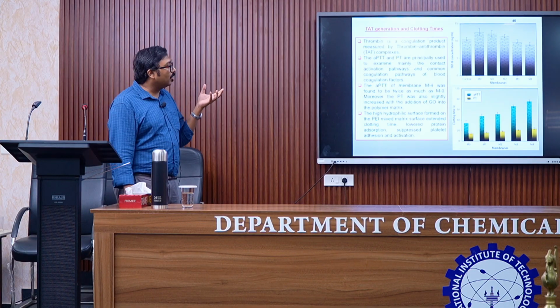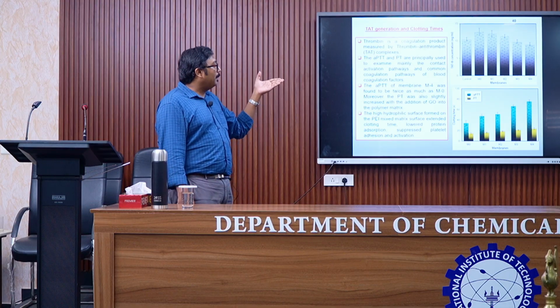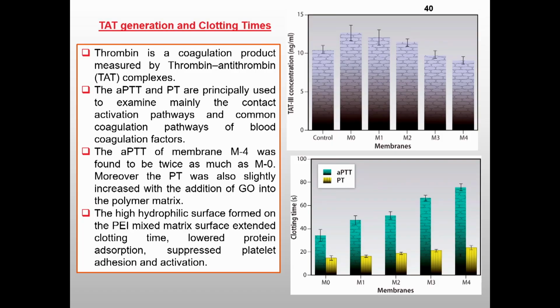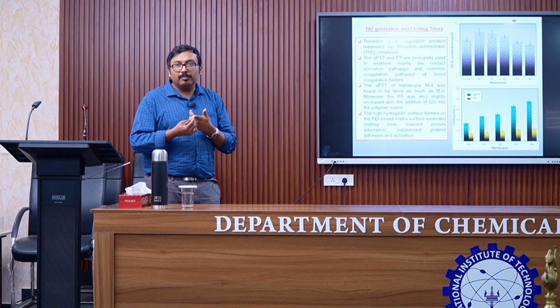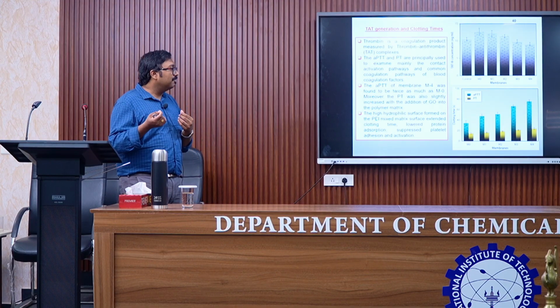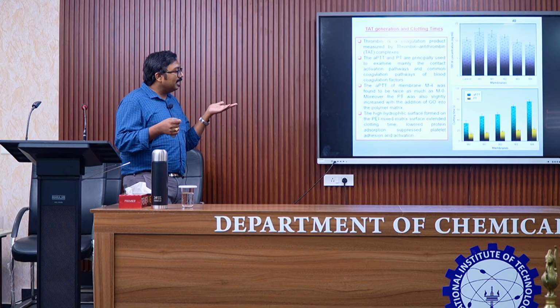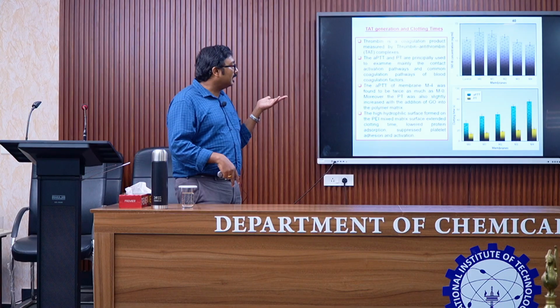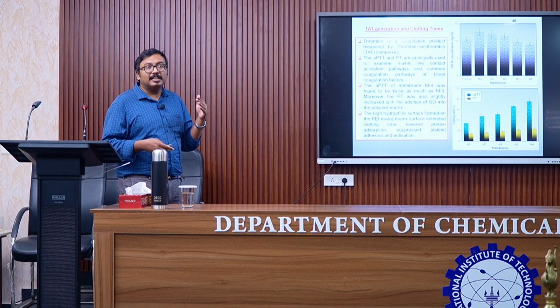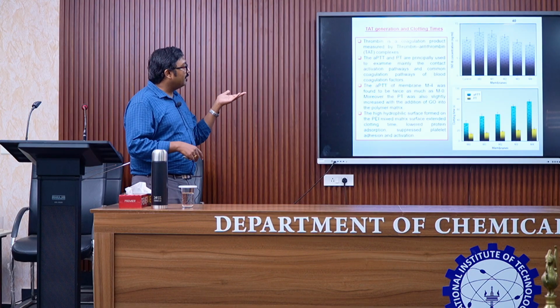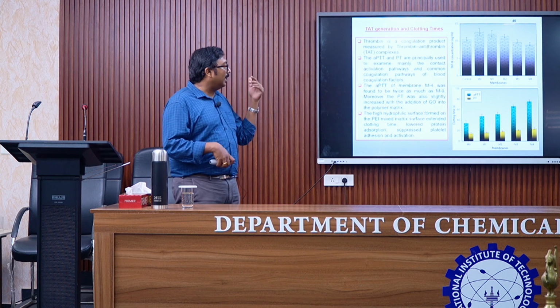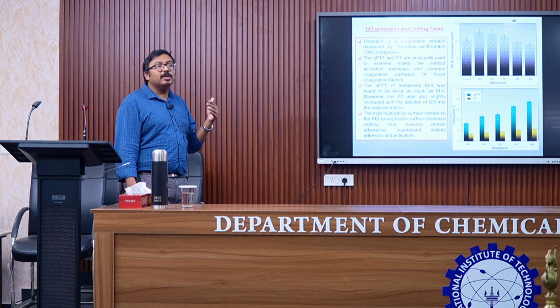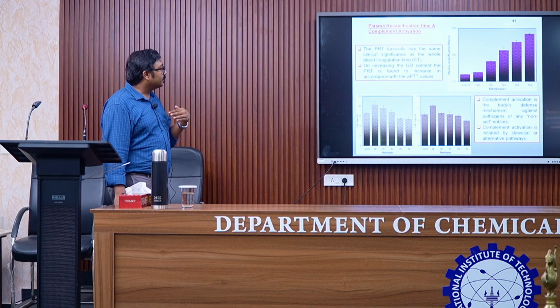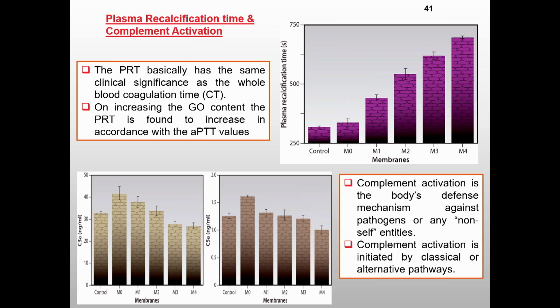TAT stands for thrombin, antithrombin, again an indicator of clotting. And APTT and PT are activated partial thromboplastin time and prothrombin time. So these two are indicators of clotting time. So ideally, a drop of blood would clot in some time, for those of you who have noticed. When it clots, it becomes much more sticky or much more viscous before it finally hardens. So an increase in clotting time is desirable because it helps the blood to flow through the entire filter without clotting in between. But there is not a very significant increase, from around 37 seconds to just around 80 seconds. So there is not much significant increase, but again, we don't want it to decrease even if there is no significant increase. This C3, C5 are two complements.